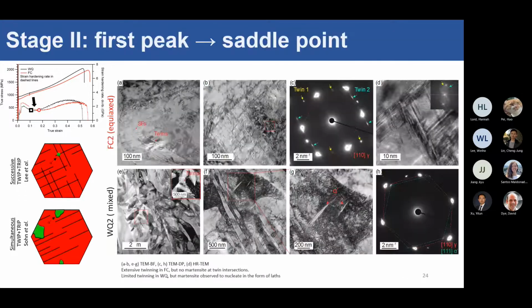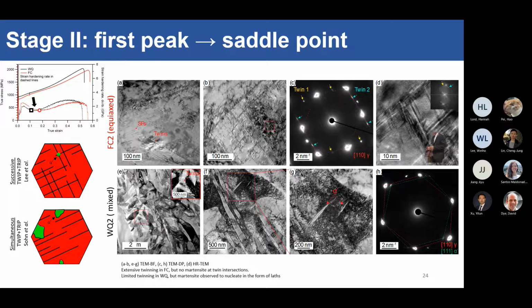Right. Now we move to the saddle point. And in the saddle point, you can see in the FC sample, you have twins going one way, and then you have stacking faults going in another way. And in another austenite grain over here, you can see the very beautiful double twinning system. So you've got two twinning systems being activated there. And when we look at the twin intersections, there's no martensite there, okay? So it's quite interesting. But literature says that at this point here, we should be starting to form some martensite at the twin intersections, but we didn't find any.